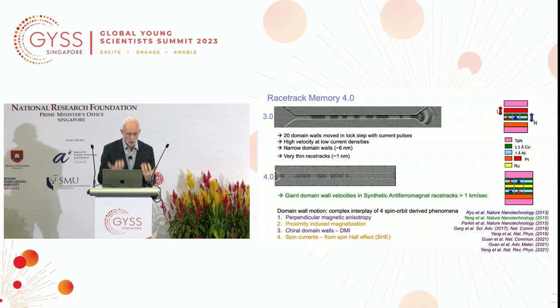So this is because of chirality of the domain walls. If we could not control the chirality, the domain walls would be moving in random directions. They only move in the same direction with current if they have the same chirality, and it's based on spin currents derived from this spin Hall effect. This is what makes it possible.